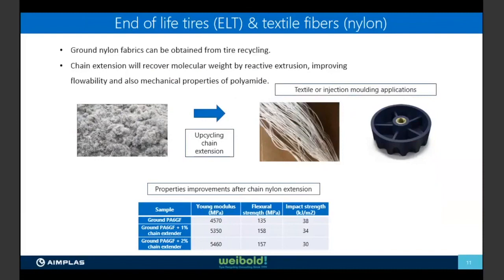So what we can do here is what is called chain extension of nylon. By means of reactive extrusion, we can add different additives, called chain extenders, to enlarge the molecular weight of the polyamides and to recover the properties. And afterwards to use it, I think it is very challenging to obtain that kind of fabric that you can see on the right side of this map. But anyway, we can recover the properties very well and it can be used for different applications.